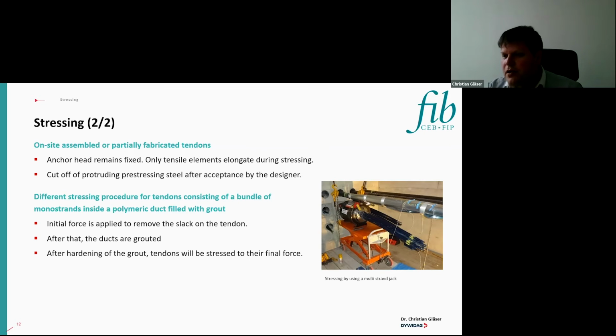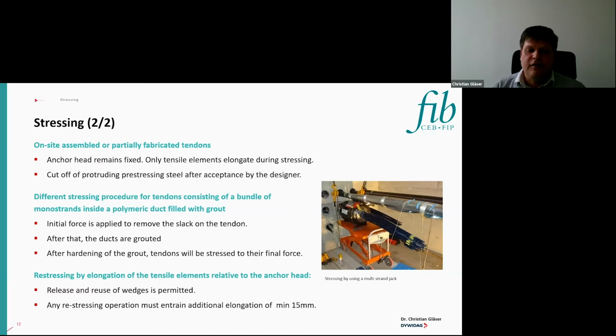Just some comment on possibly restressing. Restressing is possible as far as we can guarantee that, for example, wedges will not have the same gripping in the areas that were originally used. So it's recommended to always have an additional elongation of minimum 15 millimeters to avoid any fatigue problems in the free length.